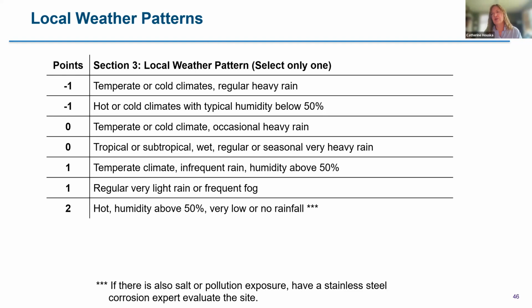And I should note, I'm mainly concerned here with a desert region on the coast, not an inland region. So if you were to look at their daytime versus nighttime humidity, the average humidity would be very low. If you look at the nighttime humidity, then you might be up at 80%. So the time of wetness, the time when corrosion occurs, is at night. So if you're not looking at those numbers separately, then you can think that you have a situation that's not very corrosive when it actually is.